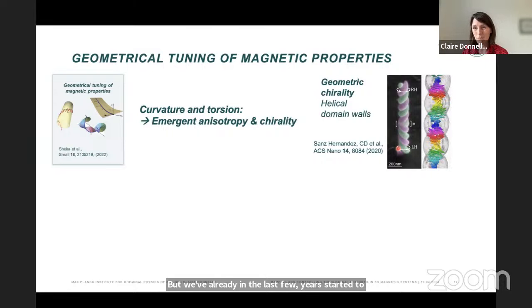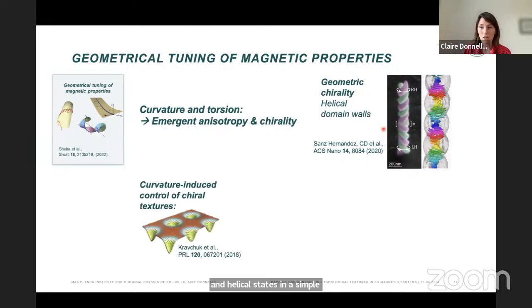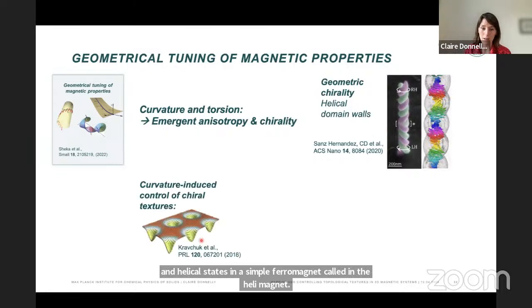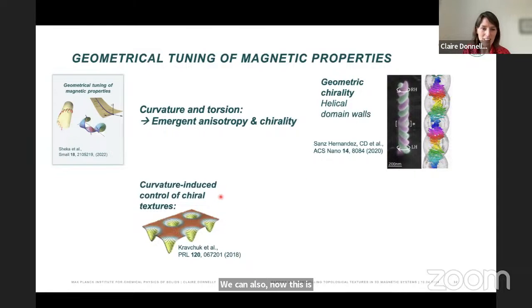So, for example, by patterning chiral geometries, we were able to stabilize chiral helical states in a simple ferromagnet rather than a helimagnet. We can also, and this was work by Vladimir Kravchuk and colleagues, introduce curvature onto a thin film, and you can locally stabilize skyrmion-like textures.